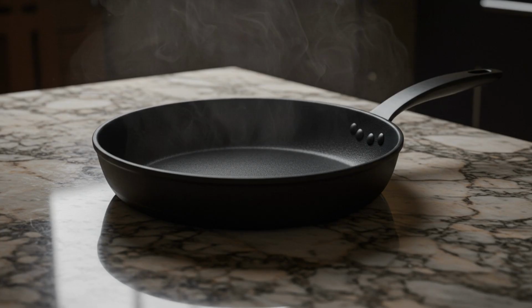The finished non-stick pan is a masterpiece of material science. What started as a piece of dull aluminum and a liquid chemical suspension is now a high-performance tool. We've used mechanical abrasion to create anchors, chemical primers to bridge the gap, and high-temperature sintering to fuse everything into a single slick surface. The engineering doesn't just make cooking easier, it makes it healthier by reducing the need for fats and oils, and it makes cleanup a matter of seconds rather than minutes.